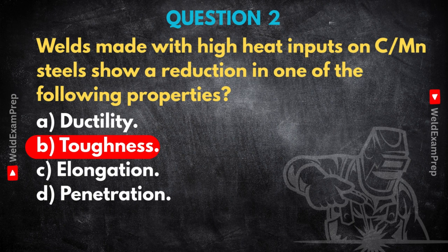High heat input means the metal stays hot longer and cools slower. This lets the grains in the steel microstructure, especially in the heat-affected zone, grow larger. Bigger grains. That sounds bad. It usually is for toughness. Think of fine grains as a tightly interlocking structure, good at stopping cracks. Coarse, large grains offer an easier path for a crack to run through. The material becomes more brittle.